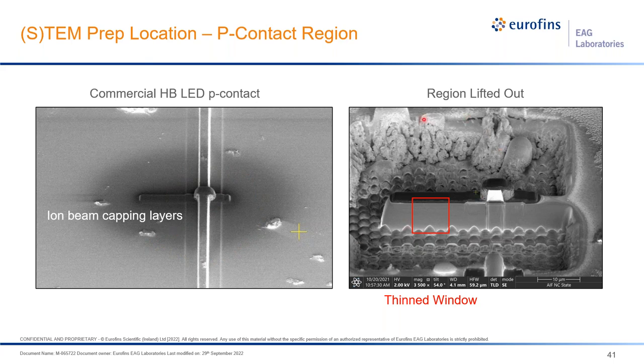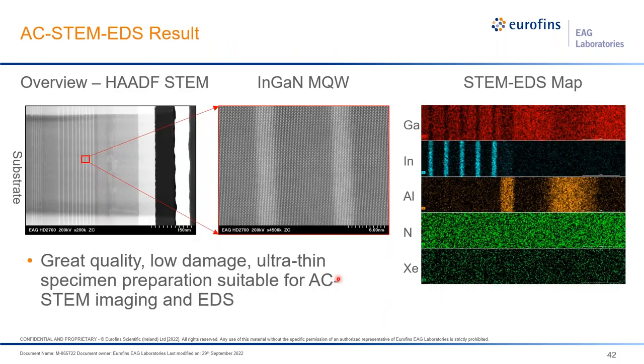So we want to understand a little bit better about what's going on in the active region, so the multi-quantum well region. We're going to deposit materials on the surface, similar to what we do in gallium FIB, but in this case using the P-FIB, and then we're going to thin a window here suitable for STEM work. Here on the left, we see an overview of a HAADF STEM data of the multi-quantum well region, and then here looking at the individual multi-quantum wells themselves.